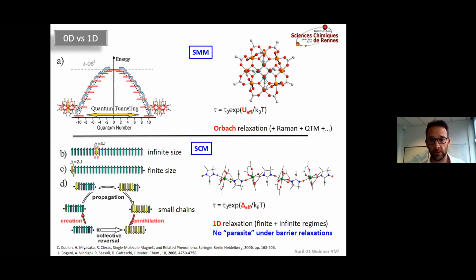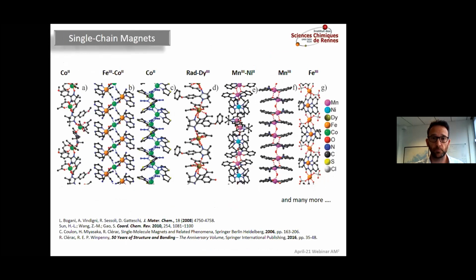In single chain magnets, we also have an Arrhenius law dependence, but this is 1D relaxation, so this is totally different. And there is the advantage of having no parasitic under-barrier relaxation in this kind of system. This is why we are interested in trying to build new single chains. There are a lot of different single chains. These are only small examples.